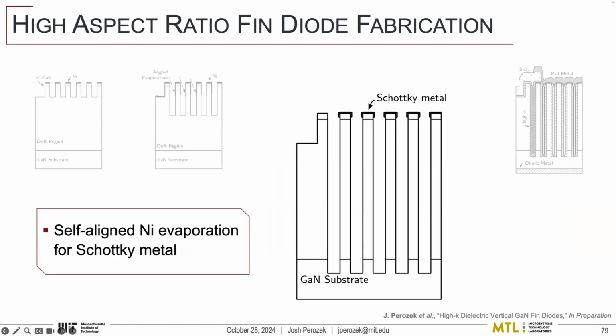If you're familiar with the Bosch process for DRIE etching, it's kind of a cyclical way of remasking your etch as you proceed, and you're able to make very high aspect ratio etches in silicon. The benefit for that is it all happens in one tool, and you can just walk away as it's a thing for a couple hours. This does take days to go through, reapply the mask, etch it down, and go through. So it's quite tedious, but in theory could be combined into one tool one day.